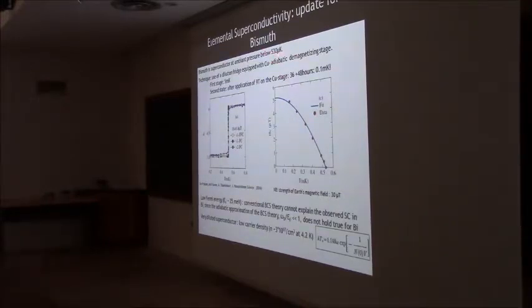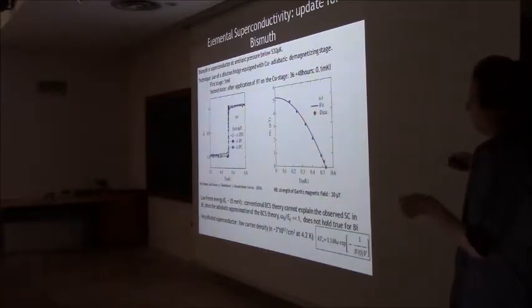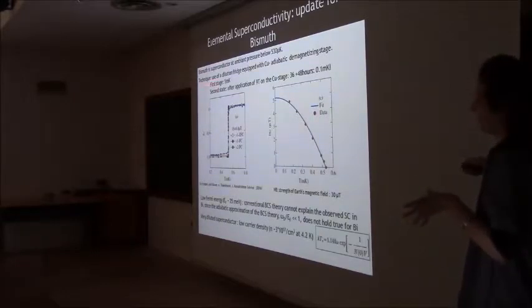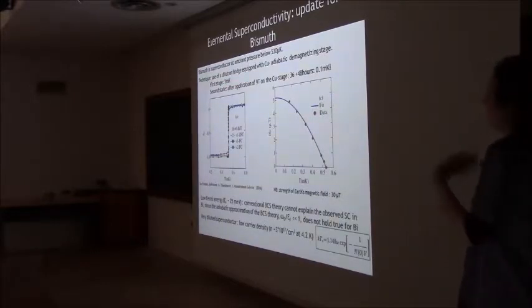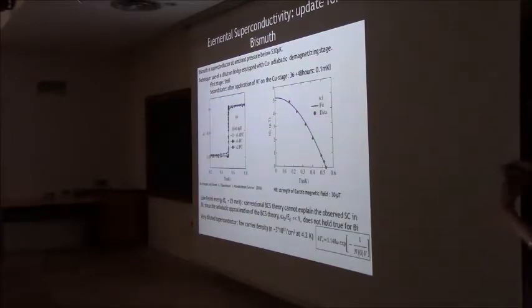So you see it's millikelvin. So just technically it's very difficult to do that. So they have a very good dilution fridge, which can first go to 5 millikelvin. And on top of that, you have a second stage, which is a demagnetization stage. And thanks to that, if you apply a very large magnetic field to this second stage, and then you wait like 3 days, then they succeeded to get 0.1 millikelvin. So it's quite an amazing experiment.